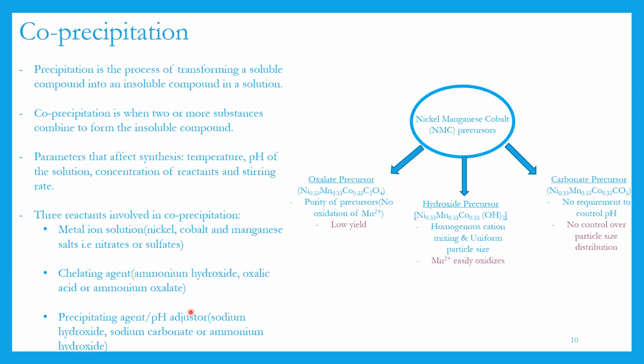So, the co-precipitation process. Depending on the ion you use to precipitate out, there are three main co-precipitation synthesis processes. Oxalate precursor synthesis is when you use oxalic acid or an oxalate to precipitate out the metal ions. For each synthesis I'll talk briefly about the benefits of using it and also the drawbacks.